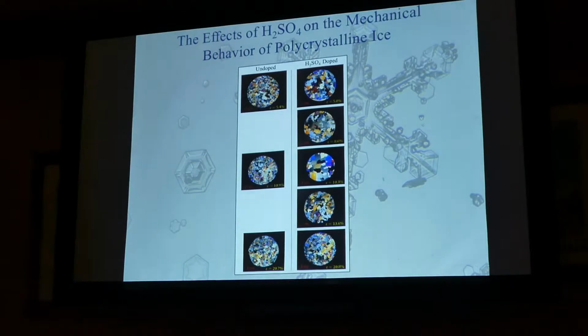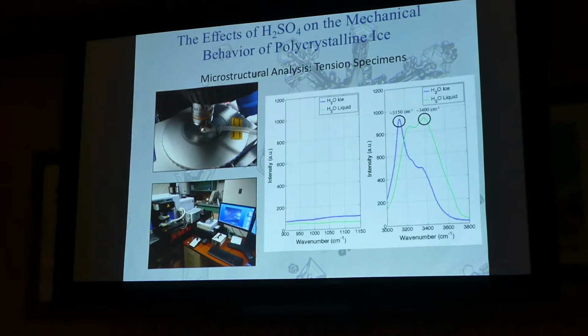And again, we saw even more extreme results in the differences. So if we look at the undoped ice, pure ice over here, and compare it to the sulfuric acid doped ice at 10% strain, these grains are a factor of 2 or 3 larger. So something very different was happening just because of the sulfuric acid being added.